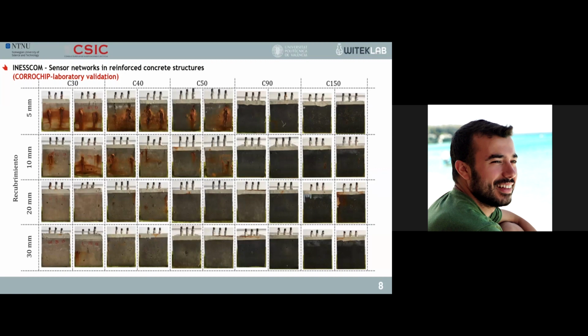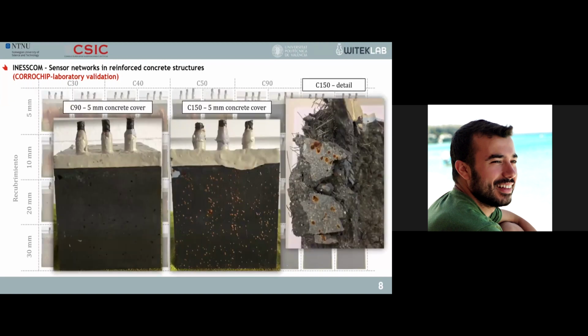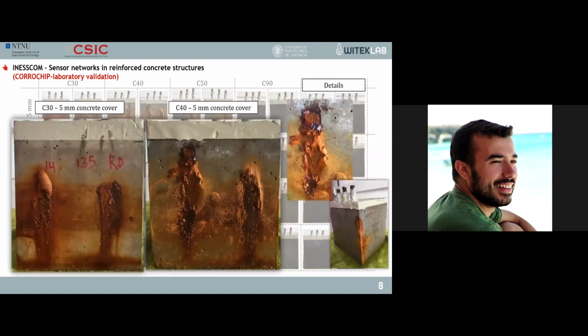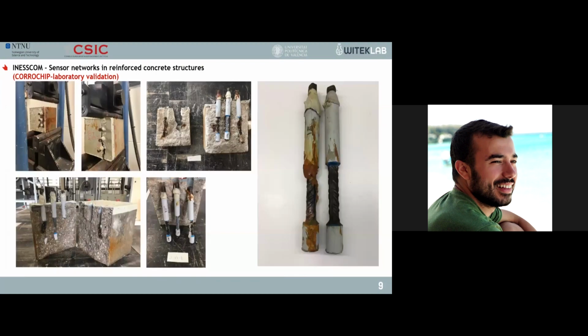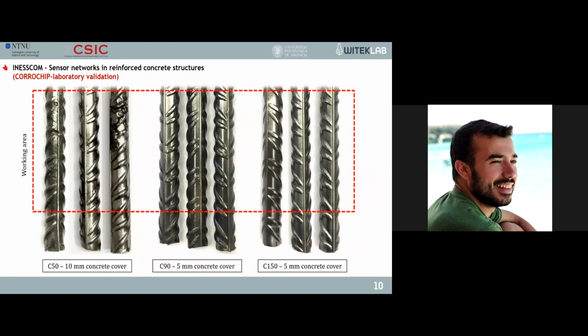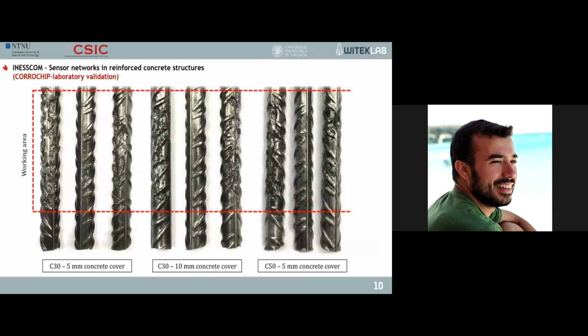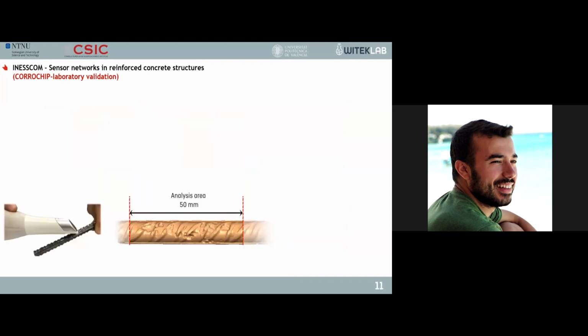First, the study was accompanied by a detailed visual inspection, classifying the test specimens according to the type of concrete and damage we found. As you can see from this picture, no corrosion was detected on ultra-high performance fiber-reinforced concrete specimens, but large rust stains and even small cracks were detected in ordinary concrete specimens. Then a visual analysis of the rebar was performed as well. The rebars were subjected to a cleaning process which revealed serious corrosion damage. In this case, significant pitting was detected.